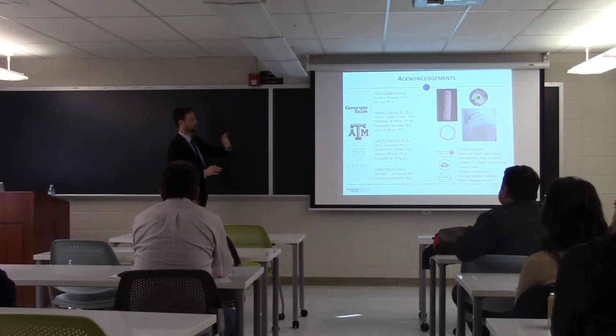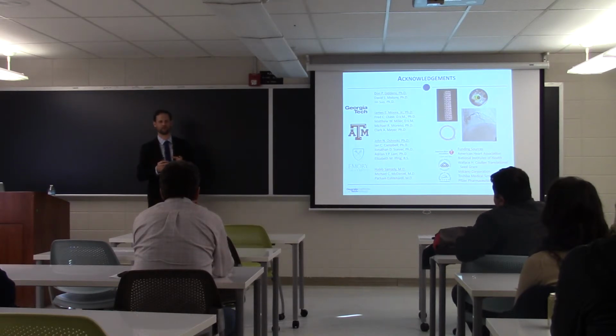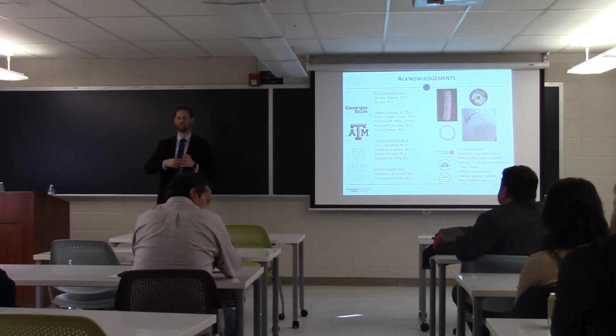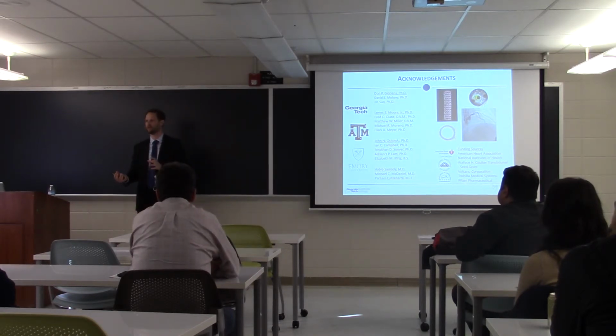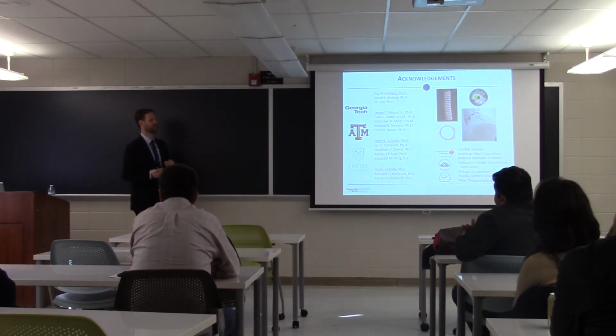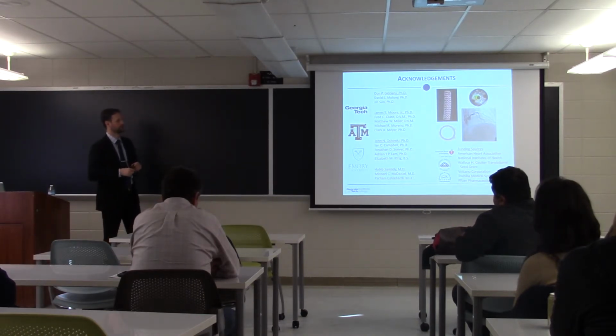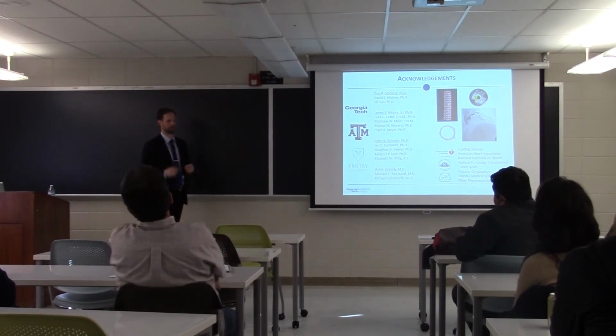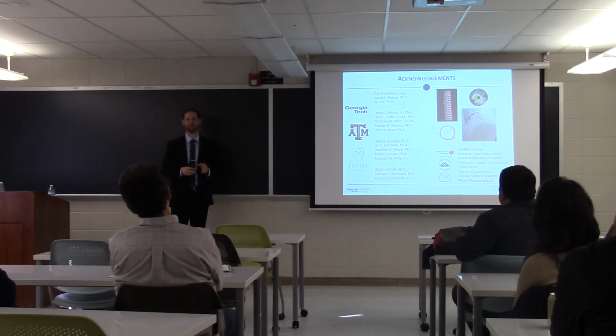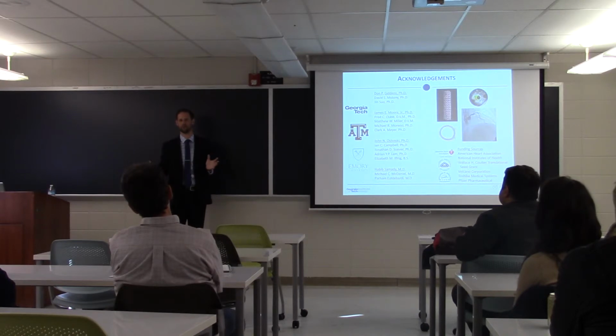What we didn't look at, and what has really moved into the interventional area, is coating these metallic structures with drugs, which are called drug-eluting stents. These drugs elute over time to really reduce that new intimal tissue proliferation. That being said, failure rates are still on the order of anywhere between 5 and 10%, and there are known failure rates of drug-eluting stents that you don't see with bare metallic stents. What's in ongoing clinical trials in the States are actually stents made out of bioabsorbable materials. So these stents are completely reabsorbed into the body over 2 to 4 years.